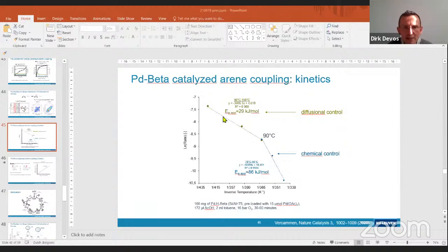Of course, at the highest temperatures, it becomes tricky to distinguish between deactivation, because maybe some slow diffusion even of the oxygen into the zeolite and so on. But indeed, at a sufficiently low temperature, you can be sure that there is no diffusion limitation. And of course, we do need the catalysis to happen within the pores, because otherwise we would never have the shape selectivity.